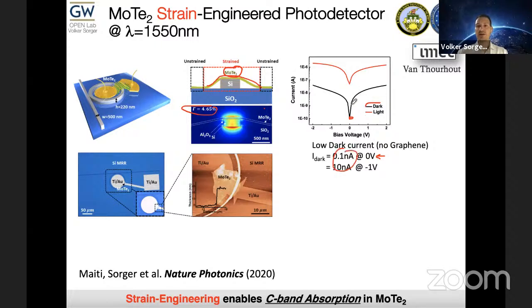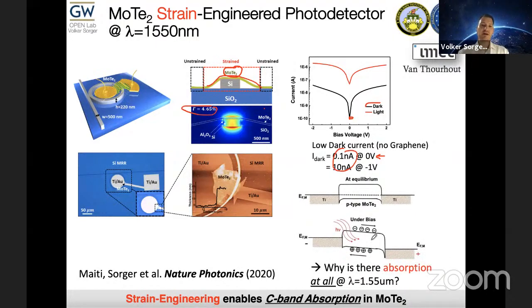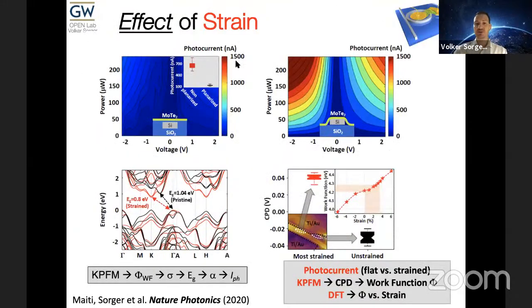And then you see the on-off ratio is about 10 to the 2, 10 to the 3. We were curious why this device actually works, because the light we send in this waveguide is 1550 nanometer. This is basically 0.8 eV. But the band gap of this MoTe2 material essentially is 1 eV. So we were in the band gap. So why did we see absorption?